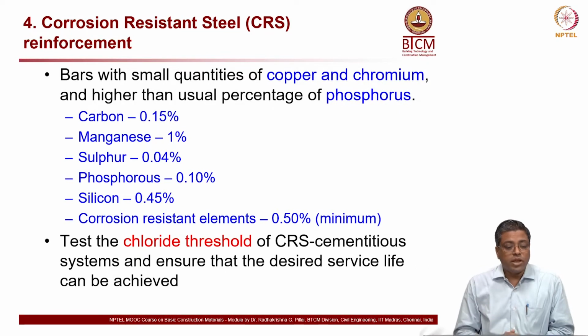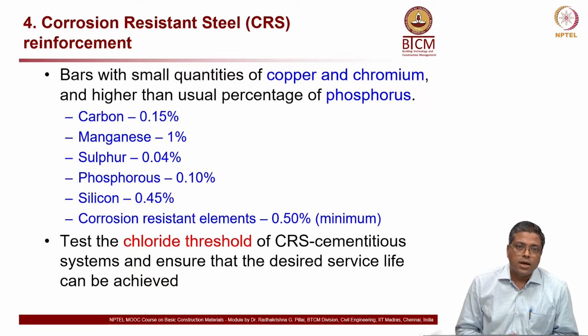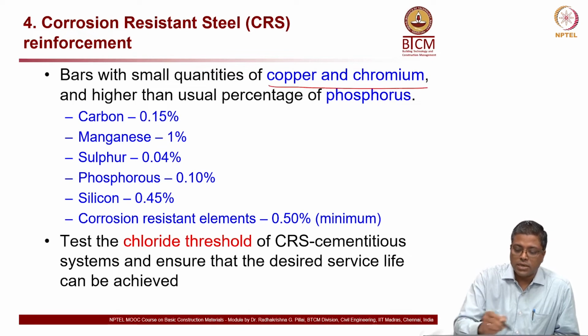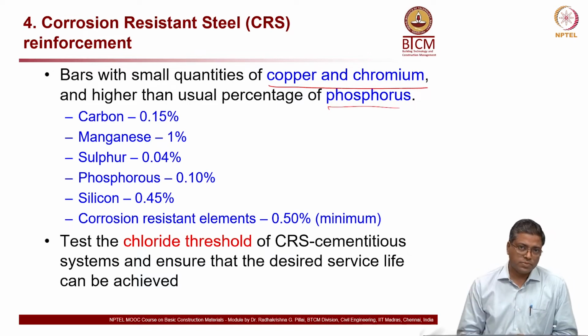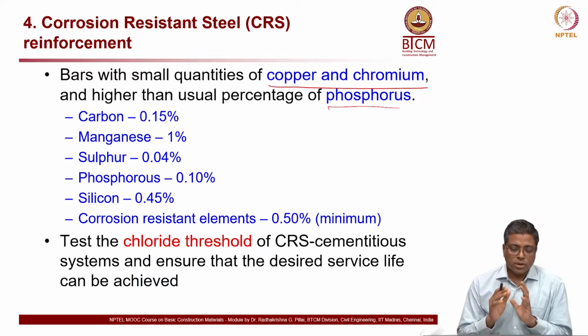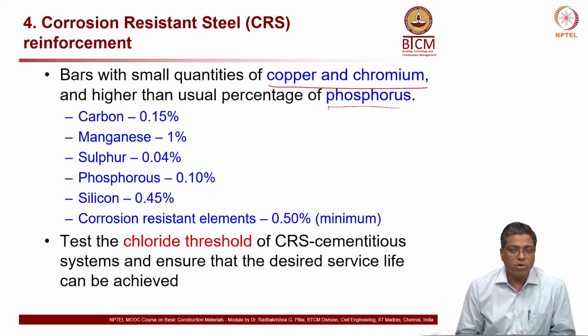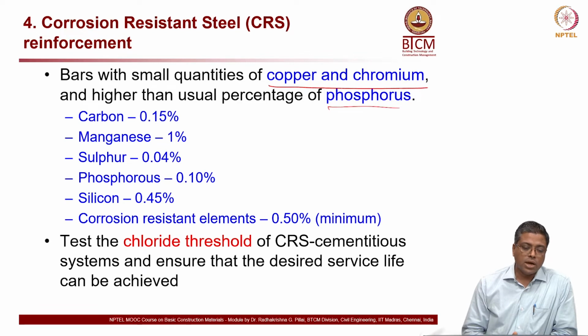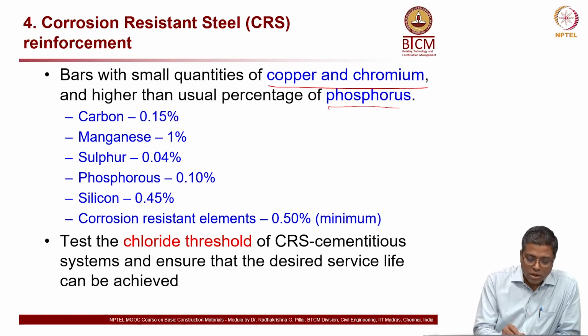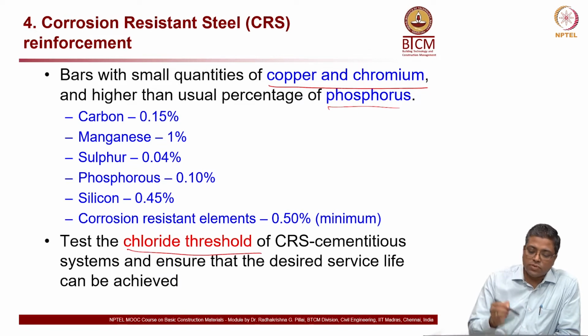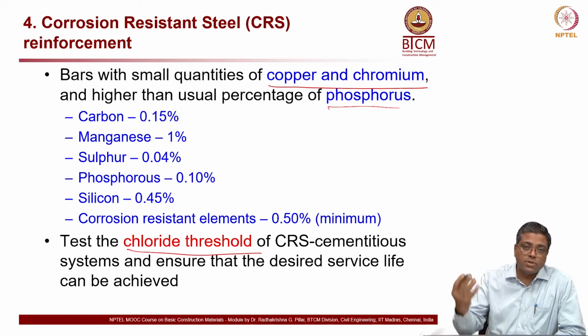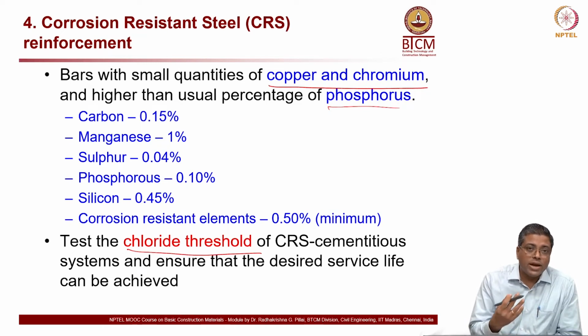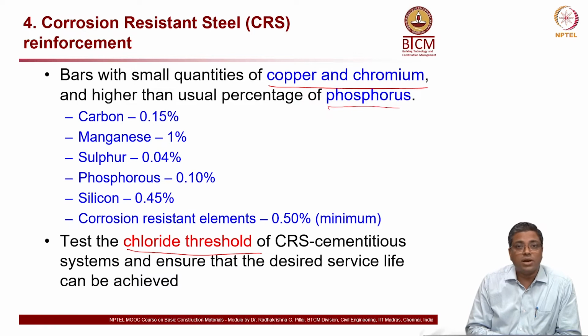Now, another type of rebar is corrosion resistant steel, which is essentially made by addition of a little bit of copper and chromium and a little more phosphorus. Okay, so these are the three additional ingredients for the steel, and then you get this rebar called corrosion resistant steel. And here one important thing I would like to mention is to test the chloride threshold of this steel, because if you look at the durability or service life of the structures, it is the chloride threshold which is more important than corrosion rate.